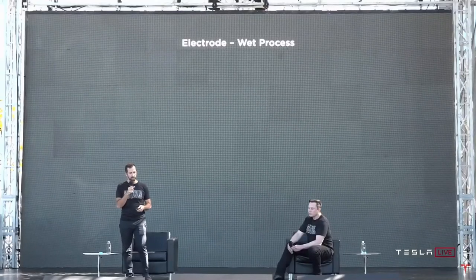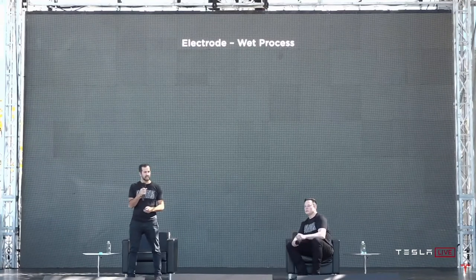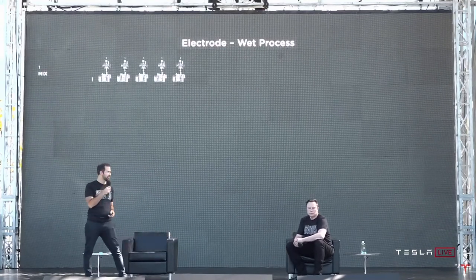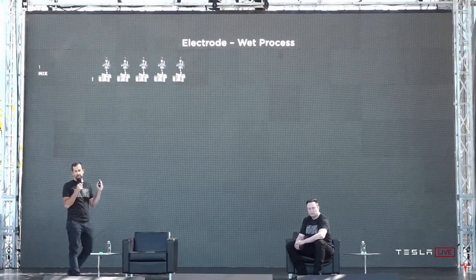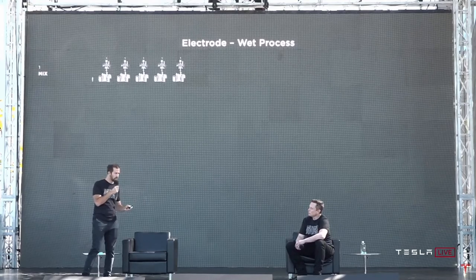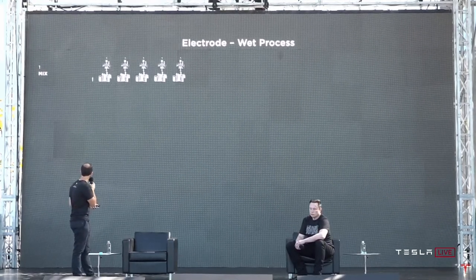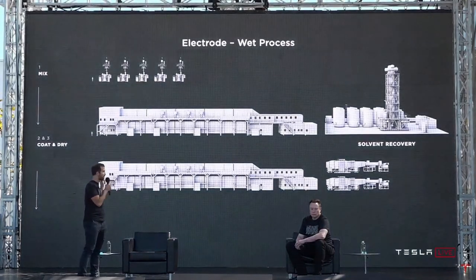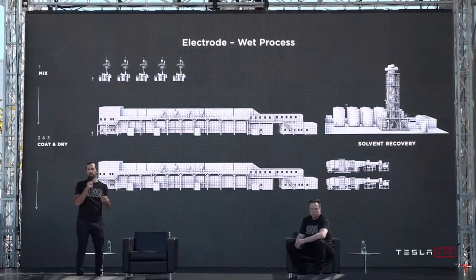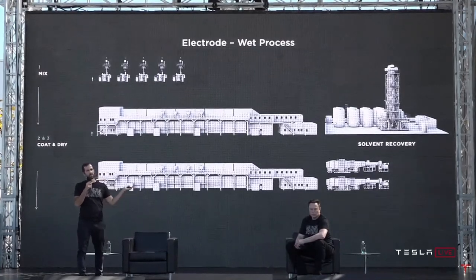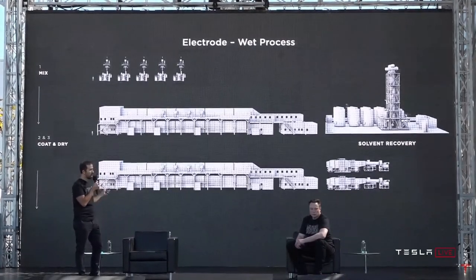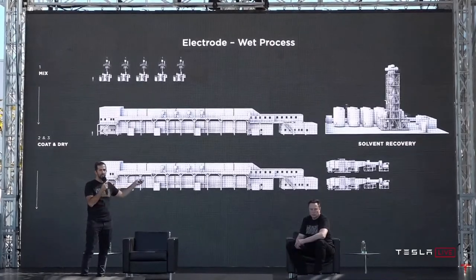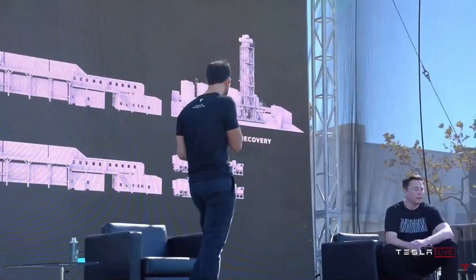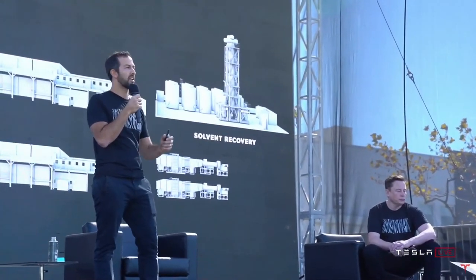And one of the most important processes is where it all begins, the wet process of the electrode coating. Just to give you all a sense of scale, I'm going to walk through what's in that wet process. You've got mixing, where the powders are mixed with either water or solvents for the cathode. That mix then goes into a large coat and dry oven where the slurry is coated onto the foil, huge ovens, tens of meters long, dried, and that solvent then has to be recovered. You can see the solvent recovery system. And then finally, the coated foil is compressed to the final density.